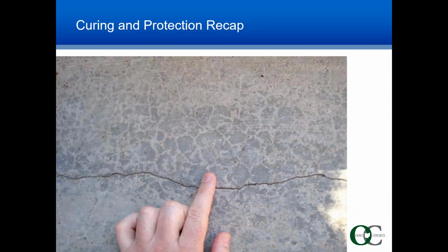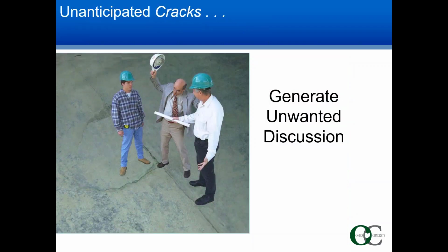Crazing is a pattern of fine cracks, shown here, that do not penetrate much below the surface and is caused by minor surface shrinkage. To prevent crazing, start curing as soon as possible. How to minimize the risk of unanticipated cracks.